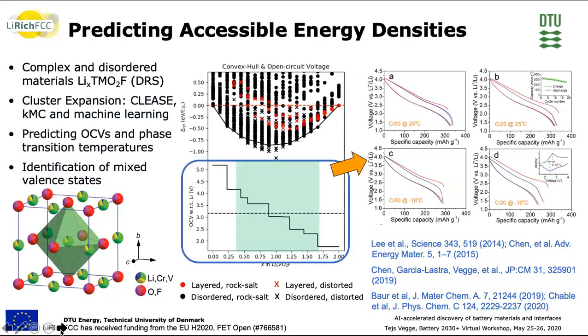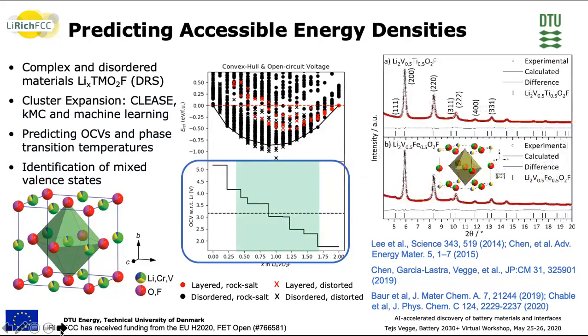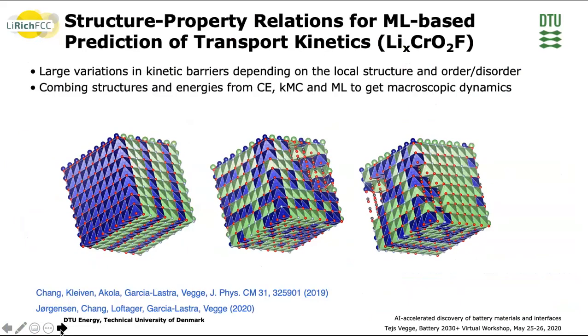So another aspect that this methodology enables us to do is also to identify what happens when we start mixing transition metals. Can we identify mixed valence states inside the materials? Also give good predictions or analysis of the experimental X-ray diffraction patterns obtained. To continue along the lines of what Christina said, that we're really trying to push the materials to the theoretical limit, we can also use the models to establish structure property relations between these disordered materials and their kinetic properties, such that we can predict macroscopic transport properties of the materials using only these cluster expansion results for the structures.